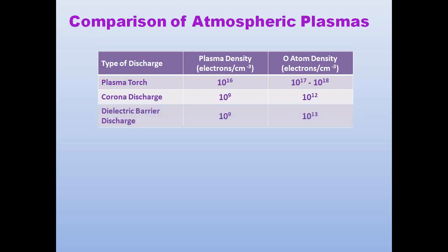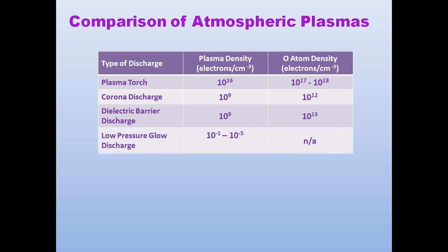When we work with modifications of these types of atmospheric discharges, such as a dielectric barrier discharge, they're going to be similar. The similar effect is because you have an anode and a cathode, and you're still reacting these gases at less than plasma torch velocity. And of course, when you're in a low pressure glow discharge or a low pressure vacuum plasma, there's certainly no oxygen density and certainly a very low plasma density. That is why the dwell time is so high, and necessarily there's been a lot of movement from vacuum plasmas into inline continuous methods for productivity reasons alone.